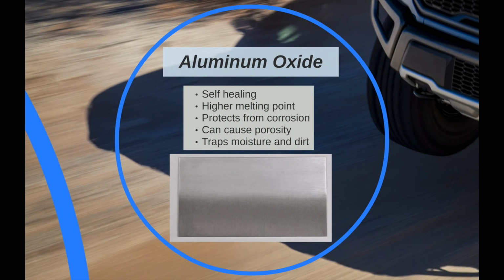Second thing is aluminum oxide. We need to understand what aluminum oxide is. When aluminum contacts oxygen, it forms a very thin layer of film on the surface of the aluminum. It is also self-healing. When you try to remove the coating, it will come back shortly. Aluminum oxide can protect aluminum from corrosion, but it can also trap moisture and dirt. The melting point of aluminum oxide is also higher than aluminum. It is 3725 Fahrenheit. Thus we have to remove aluminum oxide before welding. Otherwise, it will cause porosity or not enough penetration.